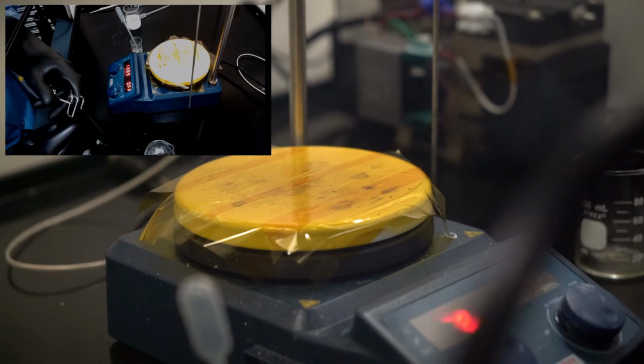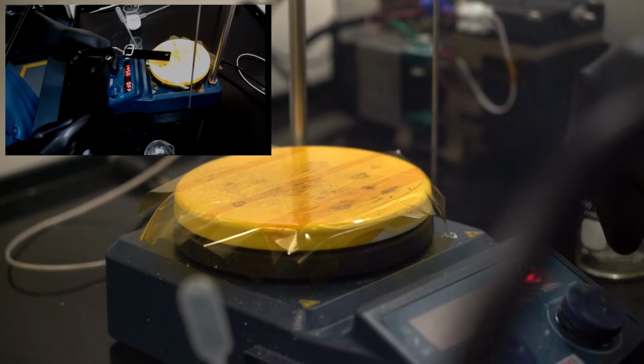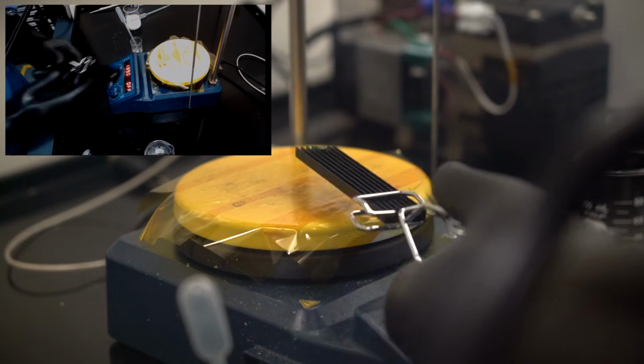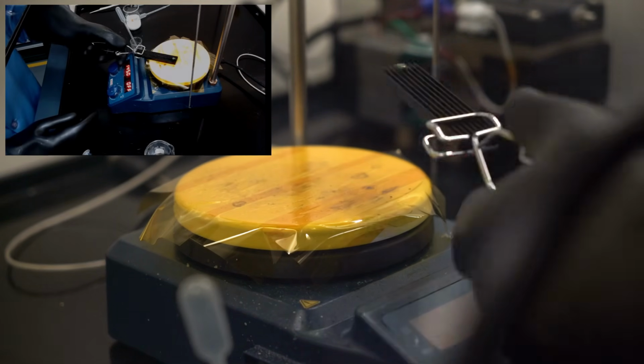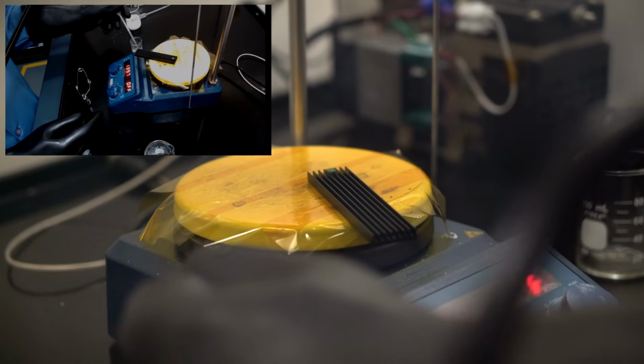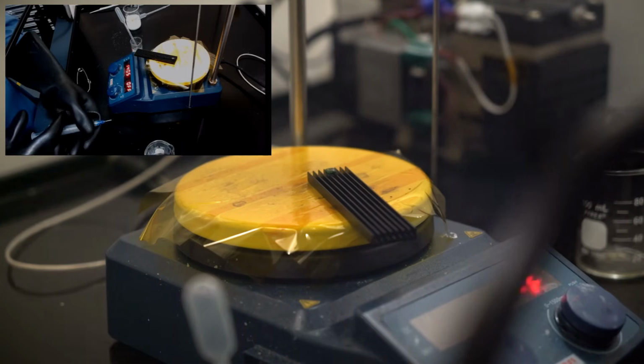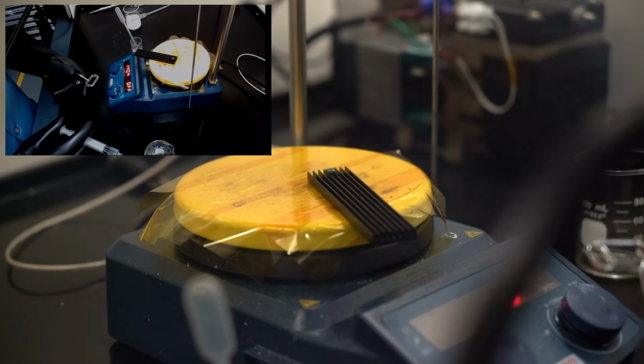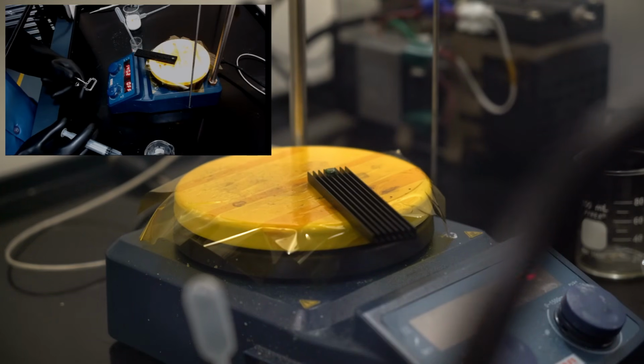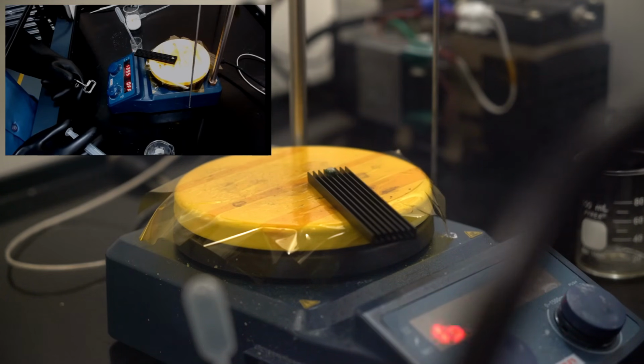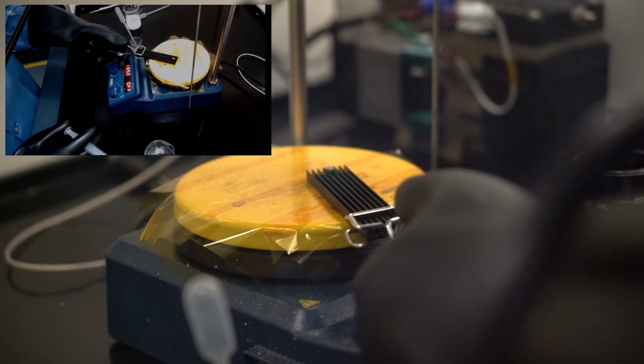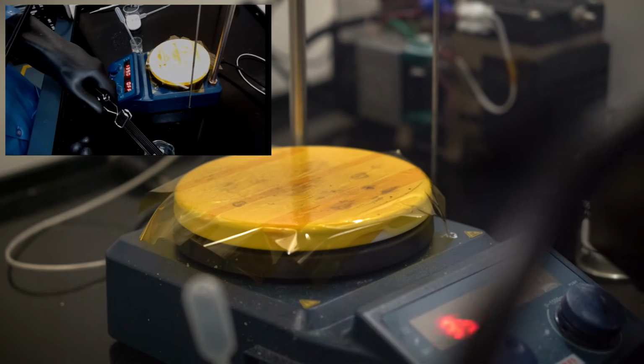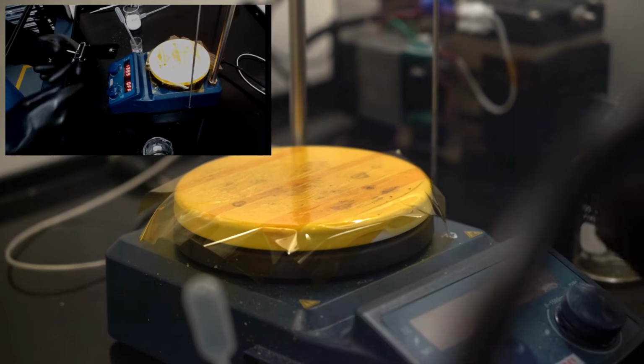And cleaning again. One of the problems I had had with previous setups was the sample delaminating from the holder, and I was using flat surfaces for that, and so the fins on the heatsink are helping with maintaining adhesion of the sample to the holder by having a little bit more contact area. The trade-off is that, as seen here, there is a little bit of acid spray getting onto the underside. I don't remember if any of the video clips actually showed it, but there was a little bit of corrosion on the underside of the sample, and so that is something I'm going to be refining a little bit further.